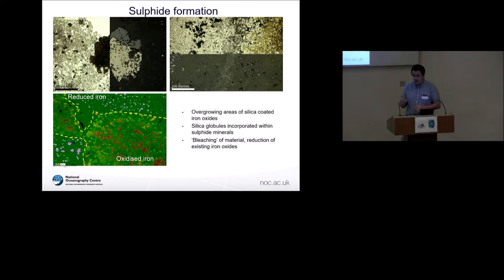And the final image is an SEM image, and you can quite clearly see the boundary between these two different types of environments. You have reduced iron, which is the pinky blobs, and then you have the actual oxidized iron itself in a different area. So there's some kind of complex fluid regime that's circulating through these systems at the end of their formation processes that's having an impact on the deposit as a whole.